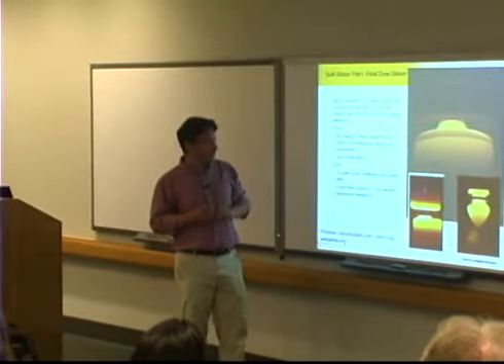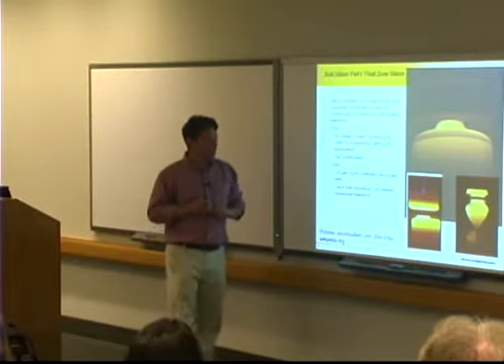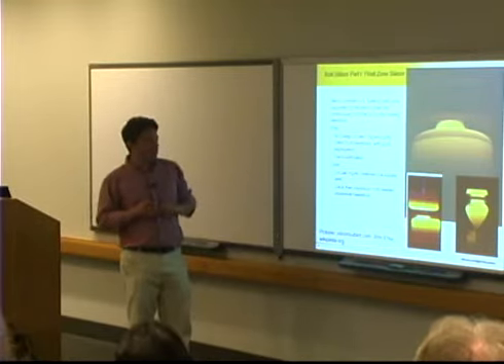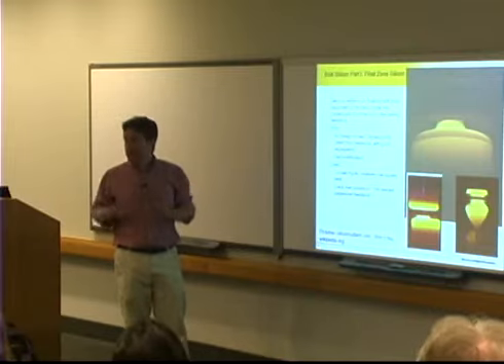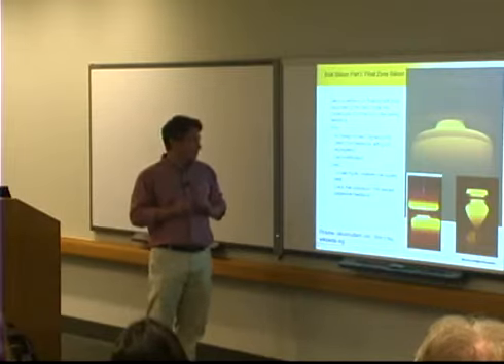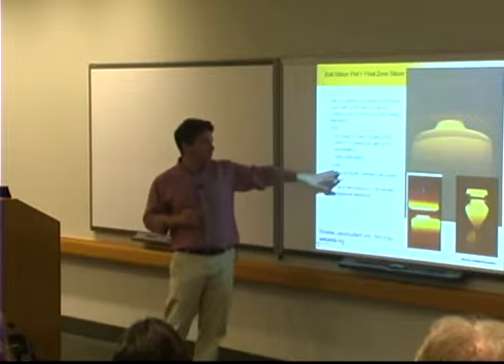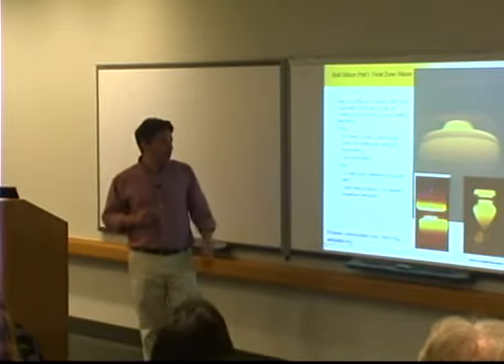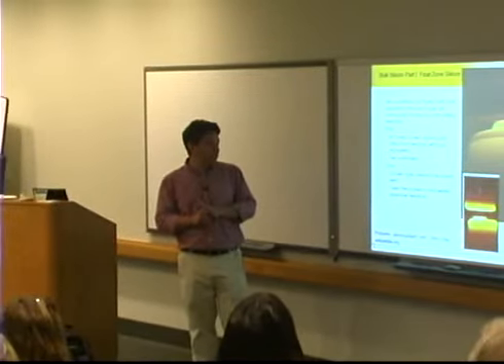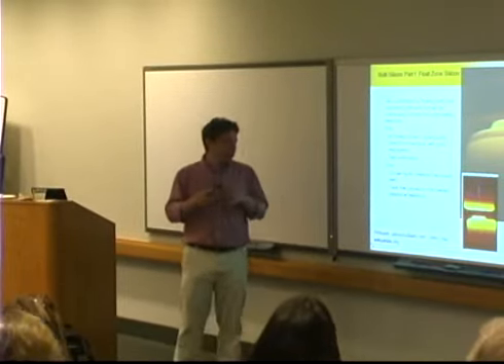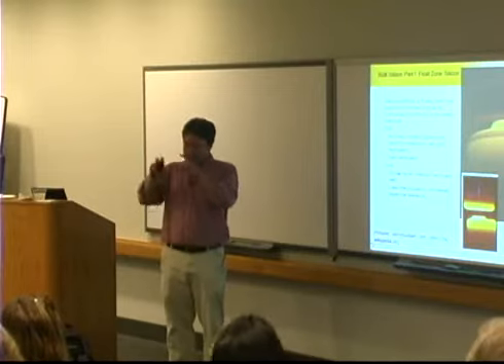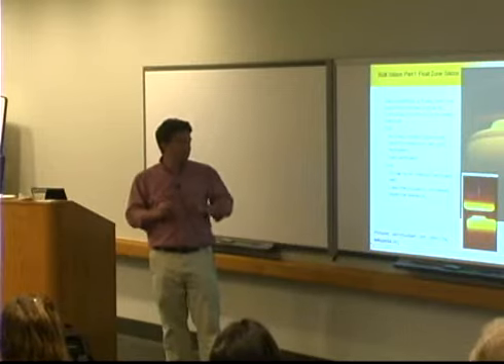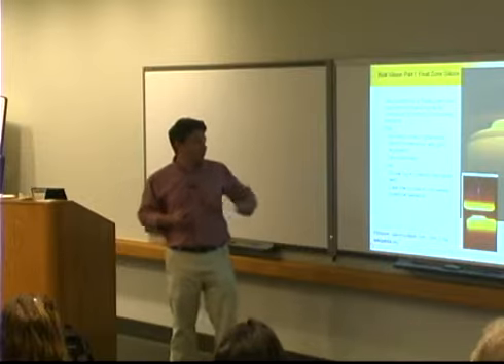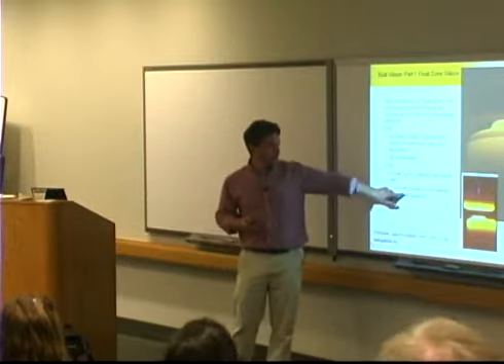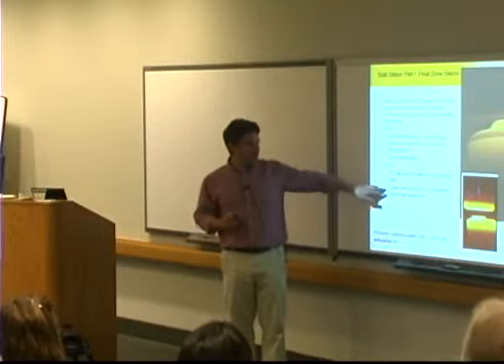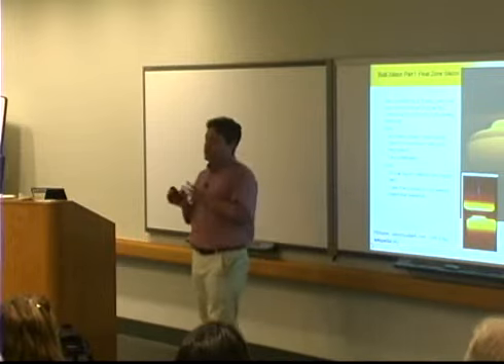And you get a lot of good things happening. It's a fast process. It's very high purity. There's no contact with any foreign materials. Single crystal, absolutely. It does still get you a circular ingot. There's a group in Germany that's been trying to make square-ish float zone, and they've gotten kind of square, but they can't do it any bigger than 4 inches. And the main drawback here is the feedstock you need. You need polysilicon rods, but they have to be grown slowly.